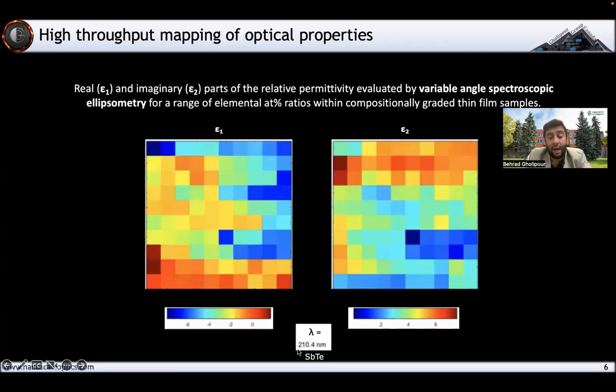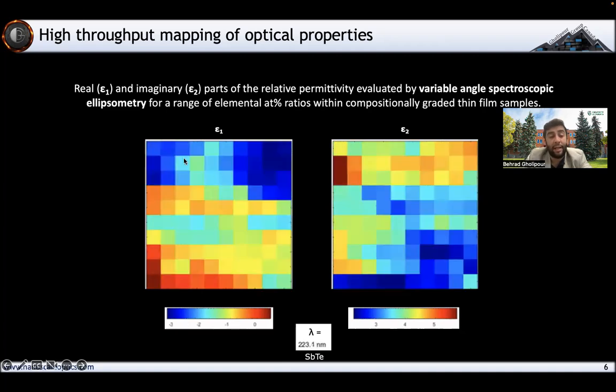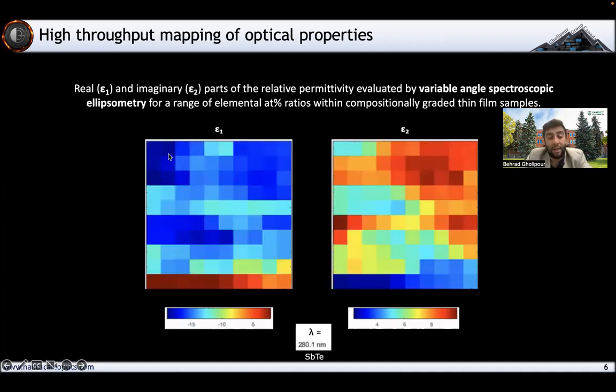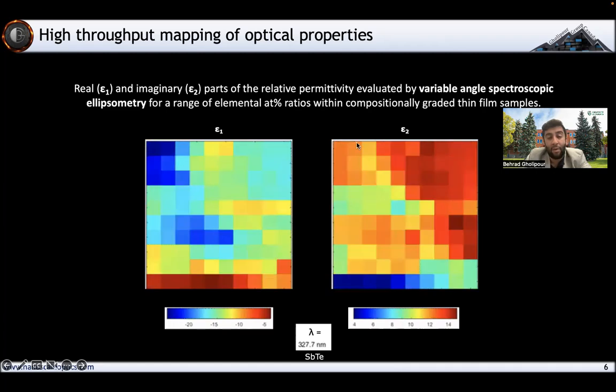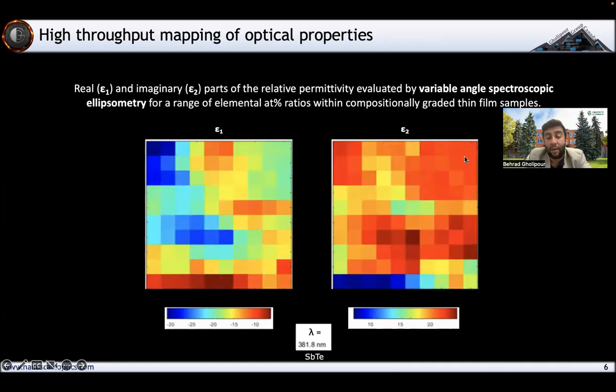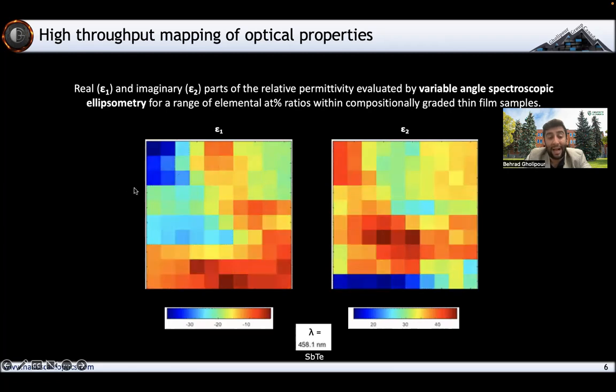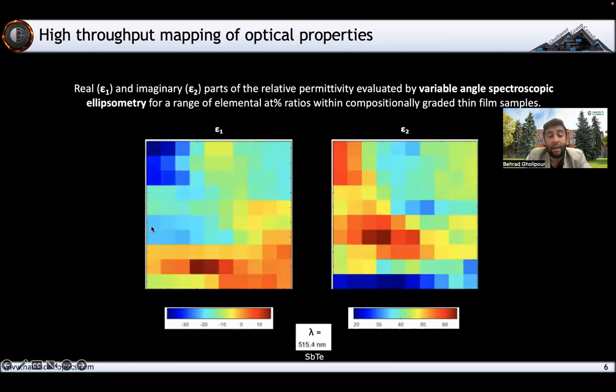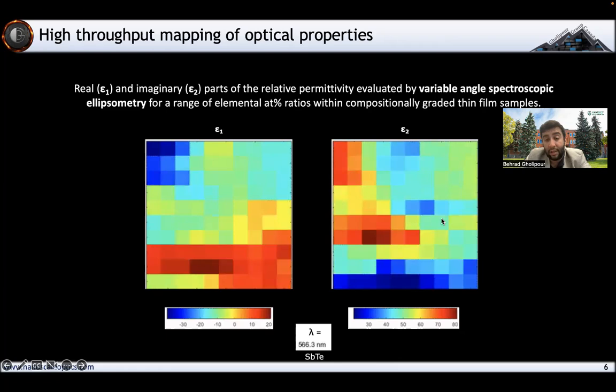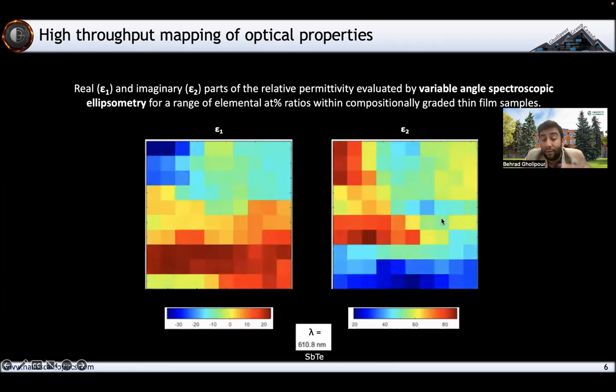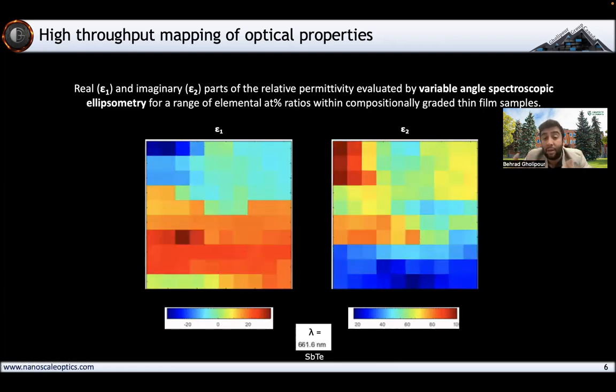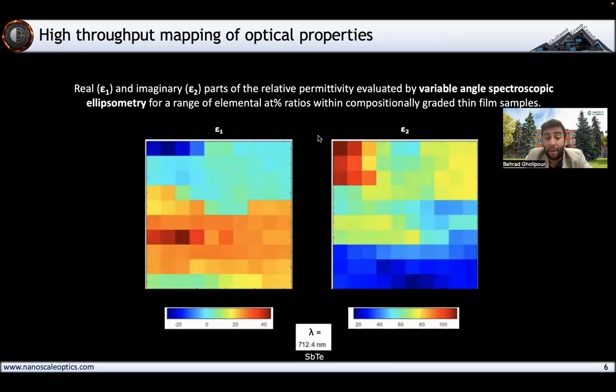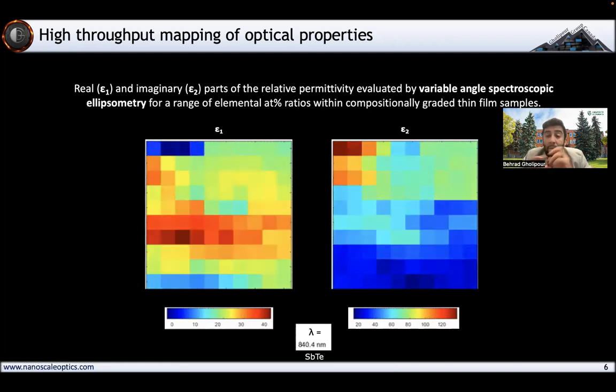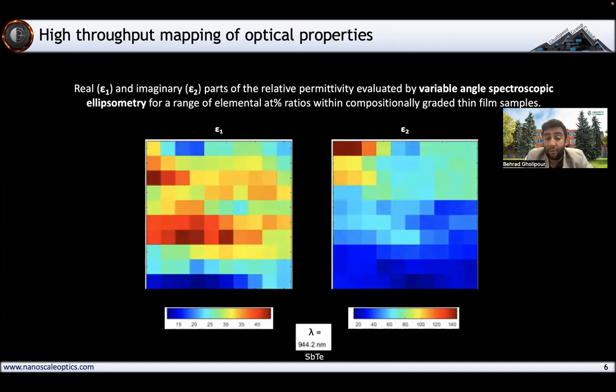And as you can see, we start from about 200 nanometers, and you can see some areas have very negative epsilon 1, some areas have very high epsilon 2, so we can identify areas where we have plasmonic properties, some areas where we have high index dielectric properties, and this allows us to design our photovoltaics and computing system components in a very, very careful way. Imagine that by just adjusting your composition, you can turn a material system from plasmonic to dielectric, and this has major implications in the operation of your devices.